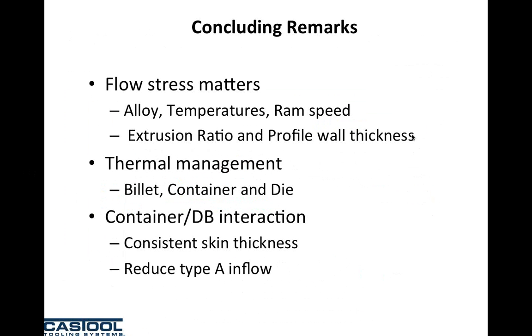Extrusion ratio and profile wall thickness I just mentioned. Thermal management of the billet, plus or minus 10 degrees. If it's precision tubing, plus or minus 5 degrees. The container plus or minus 10, precision tubing plus or minus 5, and the die the same. The container dummy block interaction is extremely important. If you're going to pay extra money for clean billet, you have to control the skin thickness, and you need to control how it is adhering to the liner. If your liner is unstable or bellied, you're going to have surface finish problems. You have no choice.